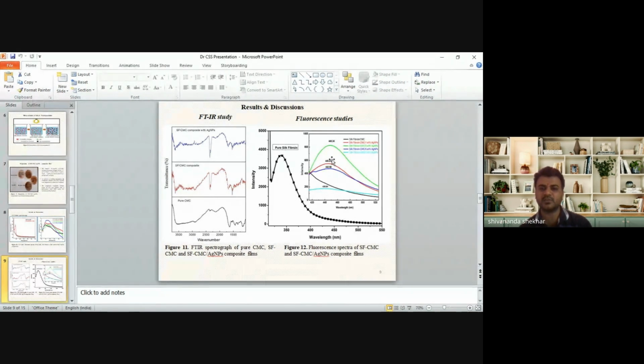So here in the fluorescence studies, we can observe the intensity of the fluorescence peak decreases as the concentration of AgNPs increases. Why? Because a greater number of tyrosine molecules reduces the Ag ions to Ag neutral atoms. So the intensity of the curve decreases due to the increasing concentration of AgNPs.